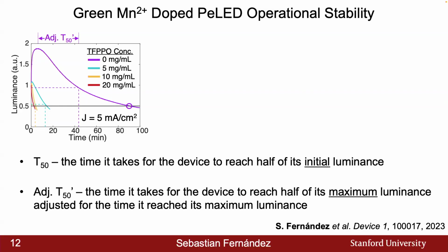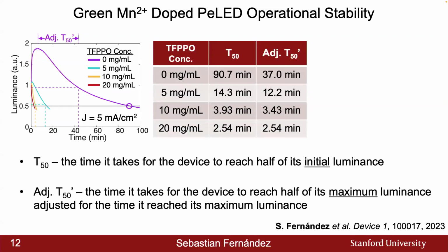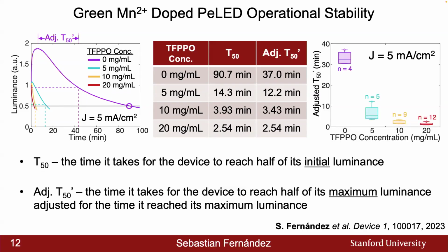And so if we extract the T50 and the adjusted T50 prime lifetimes across TFPPO concentration, the trend is actually the same. And that is, as we increase TFPPO concentration, we actually see a reduction in the stability within these devices. And again, across device statistics, we can say that definitively this is not a one-off case. This is actually truly happening within this platform.